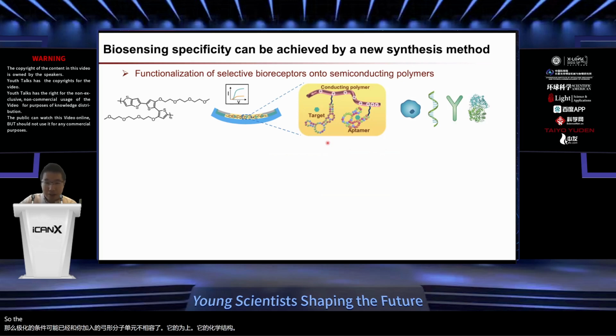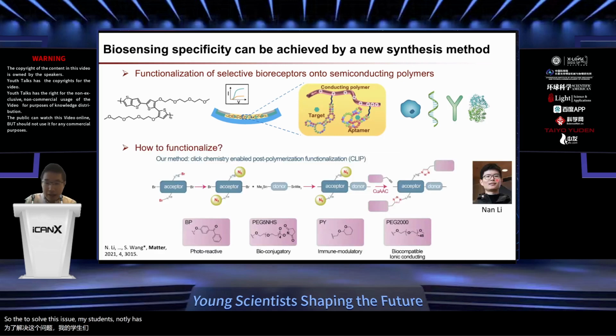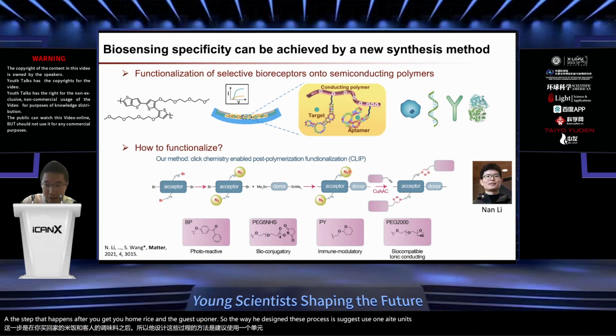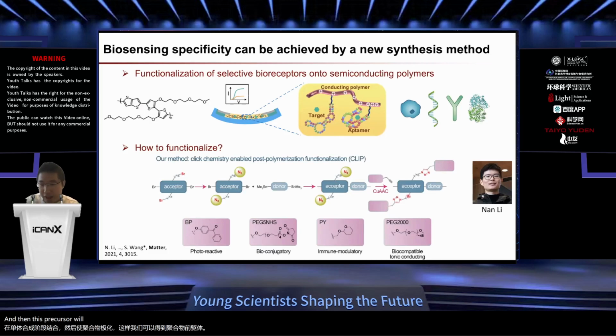To solve this issue, my student Nan Li came up with the idea of using click chemistry as a step that happens after you polymerize and get the polymer. The way he designed this process is to just use one azide unit to incorporate during the monomer synthesis stage, and then polymerize the polymer so that we can get a polymer precursor. This precursor will then allow just a one-step click reaction for the functionalization of very many different types of functional units onto the side chain. This makes the synthesis, on one hand, happen at a very mild condition to broaden its compatibility for different structures, and on the other hand, also makes the synthesis much simpler.